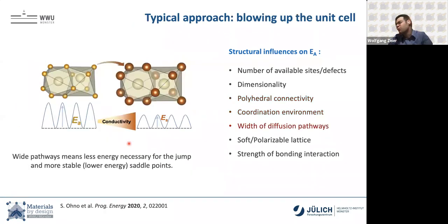And one of the typical approaches, I would say, that we have in ionic conductors is let's just blow up the unit cell. Because if displacing the lattice is what costs a lot of energy and what gives us our activation barrier, then let's just make larger unit cells, so broaden the diffusion pathways. And in most materials, this broadening of the diffusion pathways gives you a lower activation barrier. Now, so this is truly our typical playground in ionic conductors.